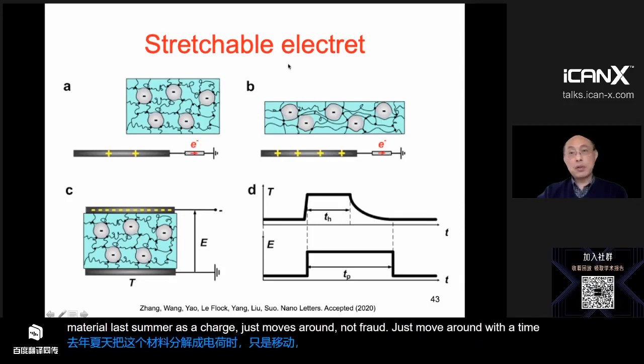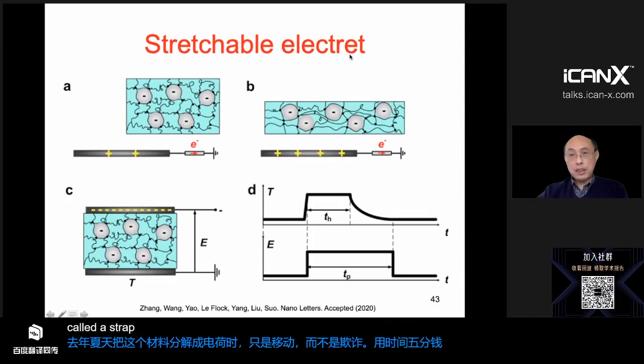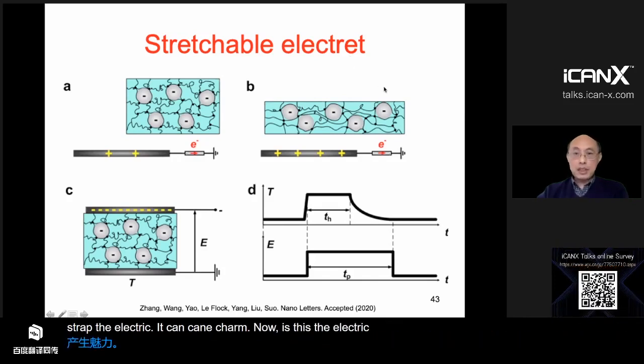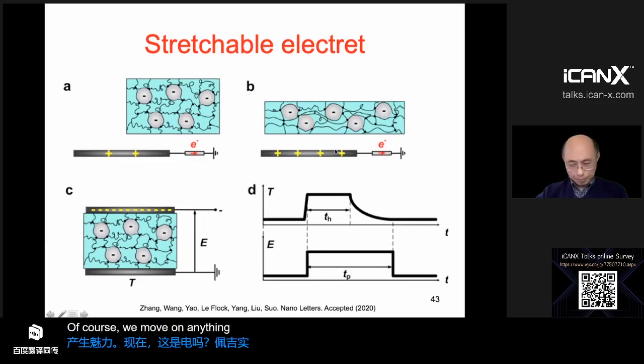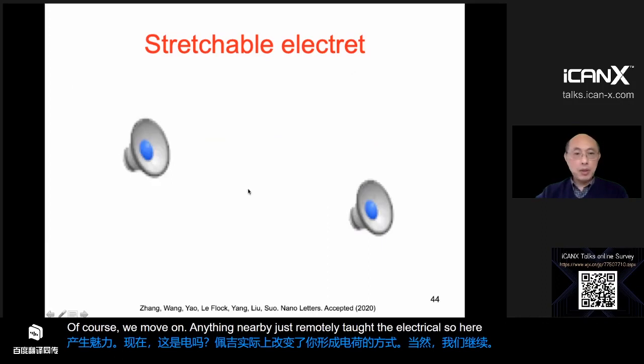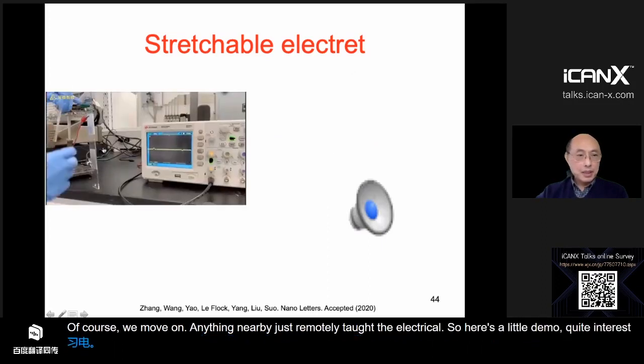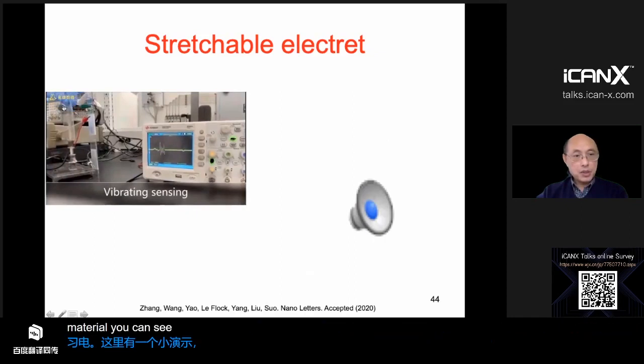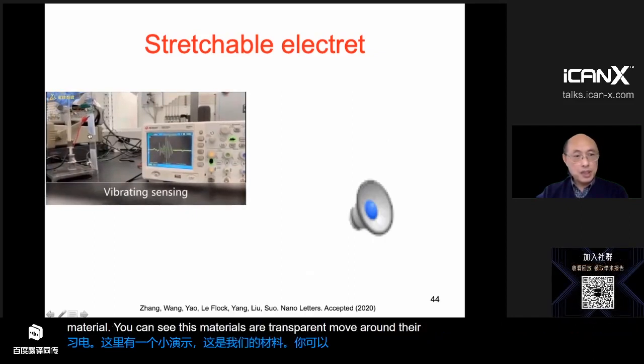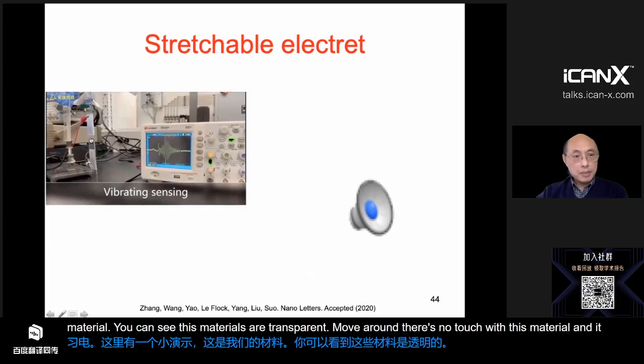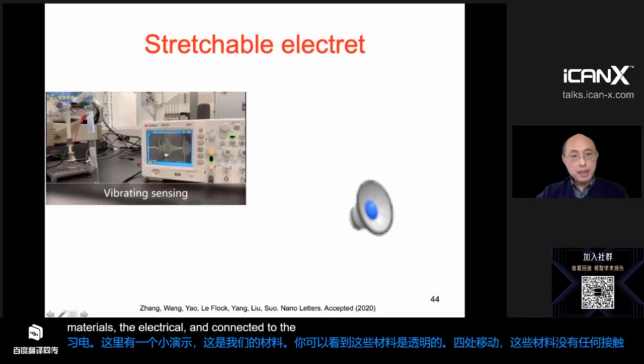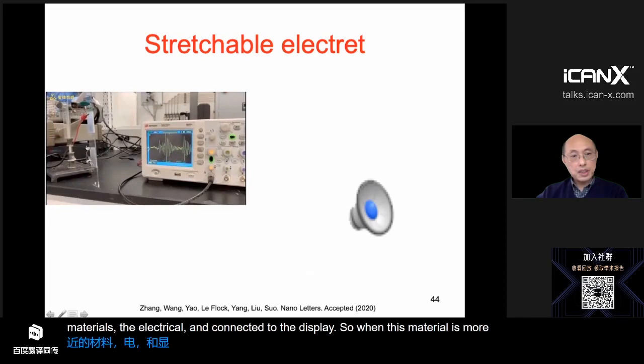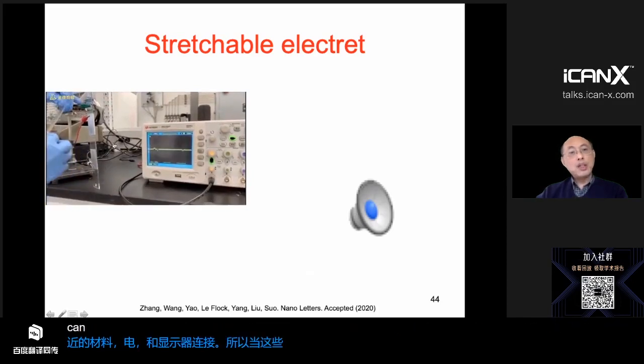So this is called an electret, it contains charge. But now this electret can be largely deformed. And when you deform charge, of course, you influence anything nearby, just remotely, electrically. So here's a little demo, which is quite interesting. Here's our material. You can see this material is transparent and moves around. There's no touch with this material. And this material is electrically connected to this display. So when this material is moving, let's see this again, we can get a signal. There's no contact.